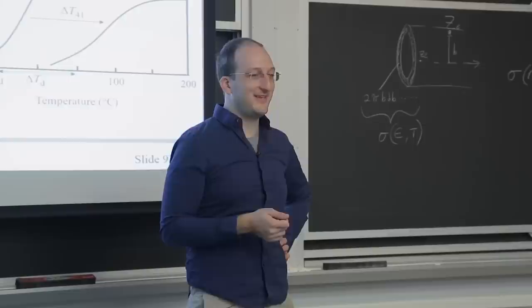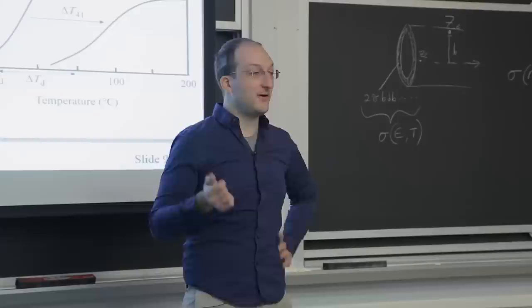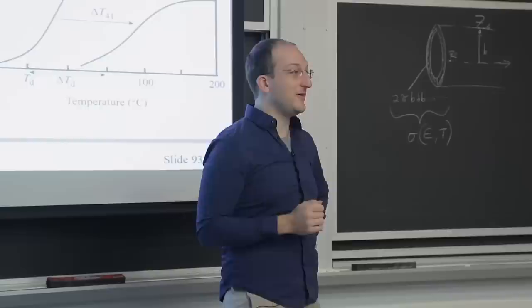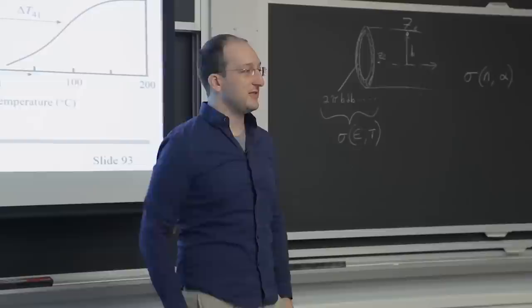Let's get into the real world stuff. What actually causes this embrittlement? Well, there's a few things. Remember we saw videos of those dislocations in a traffic jam? It's a phenomenon called pileup. These dislocations are moving and feeling each other's stress. And so they can't move as easily as they would want to. So you end up with a phenomenon called pileup. This happens both near other dislocations and near any other defect that gets in the way, like a grain boundary. So for smaller grain materials, you end up with more of this pileup. And they tend to be a fair bit stronger and they can be less ductile. But if you put anything in the way, notice this just says barrier, any other defect can act as a barrier. And this ends up shifting what we call the ductile-to-brittle transition temperature. This is the property that people worry about for reactor pressure vessels. You would want the pressure vessel, which encases the entire core of the reactor, to always be ductile in the worst possible situation. As you guys know, when you make something colder, it tends to be more brittle. So who's frozen stuff in liquid nitrogen and broken it before? So what did you guys freeze and break? Pepto-Bismol. Cool. A banana and a coin. Flowers. All these normally ductile materials become extremely brittle when they get colder. So do reactor pressure vessels.